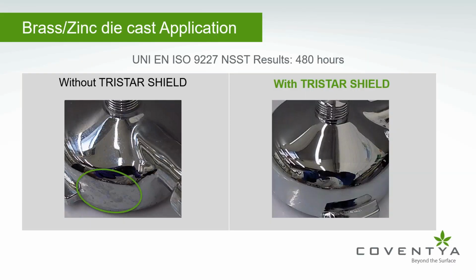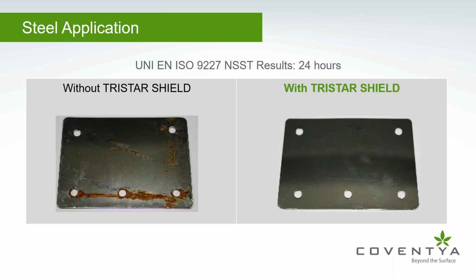Okay, now you can see how Tristar Shield on brass or zinc die cast base material helps pass the 480 hours of salt spray with no appearance of stains, holes, or other change due to corrosion. On an iron base, Tristar Shield helps pass the 24 hours salt spray test. This result is comparable to hexavalent chromium plating. As you can see from the picture, Tristar Shield managed to protect the less covered and more porous areas that are easier to expose to rust occurrence.